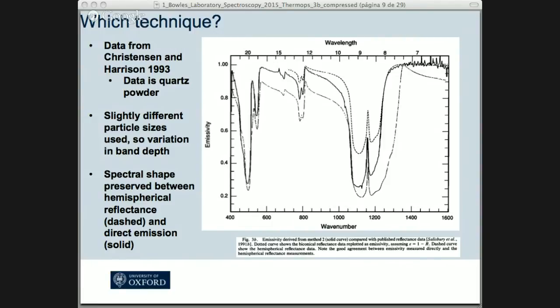If you start using biconical or ellipsoidal reflectors like in diffuse reflectance jigs, then the problem you start seeing is distortion in some of the edges of the spectral bands. This is due to polarization, orientation effects and things along those lines. There are things you can do to try and minimize that. You can see here, these two match very nicely in this region, and then it rolls off where the biconical measurements are being made, and that's a problem.